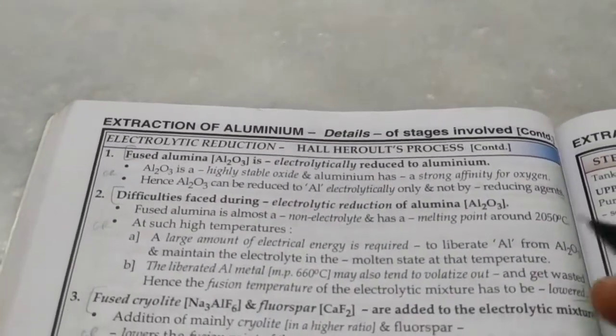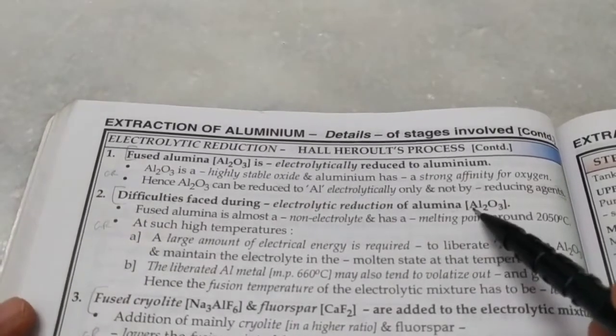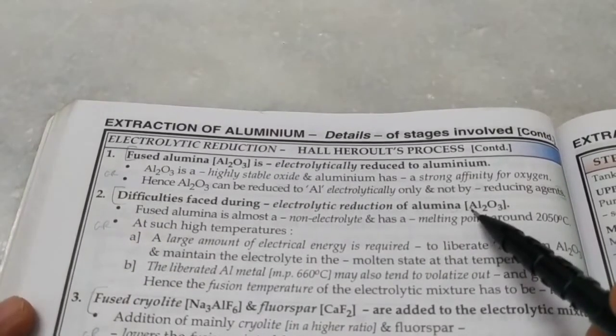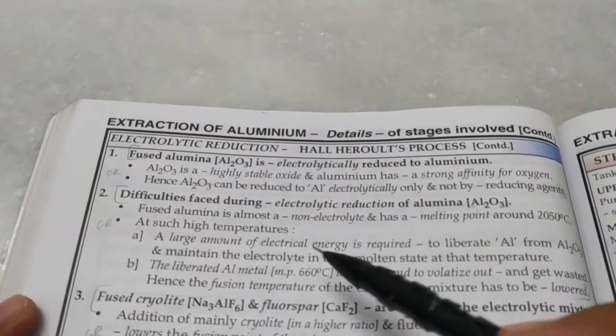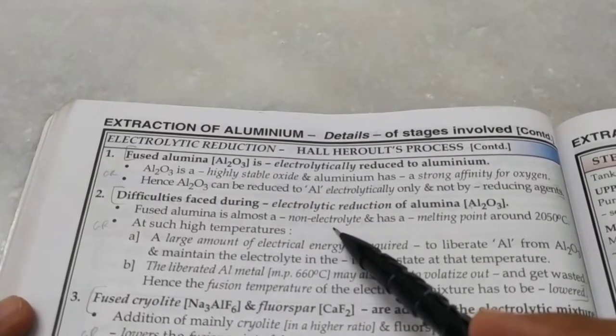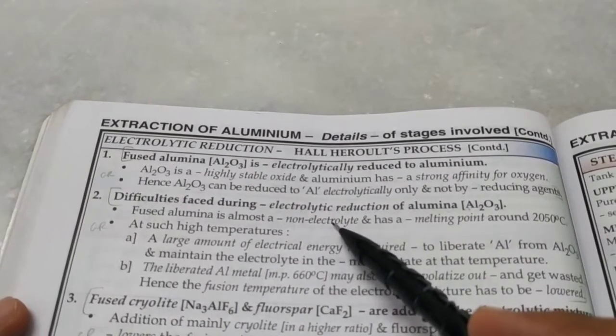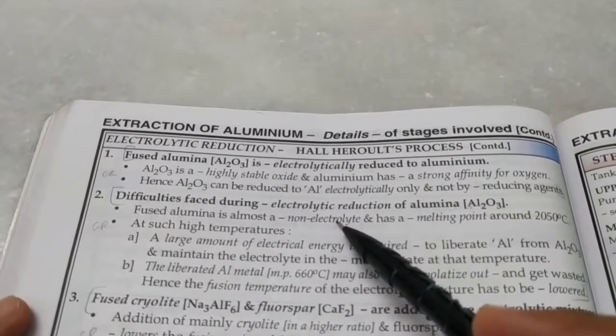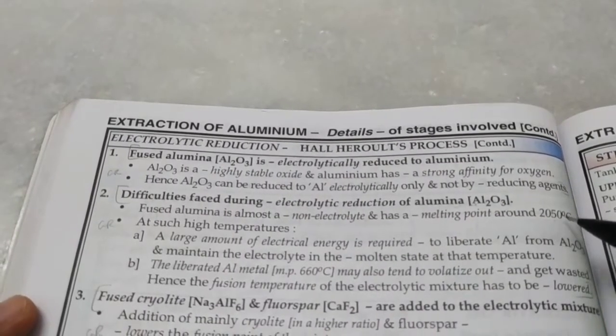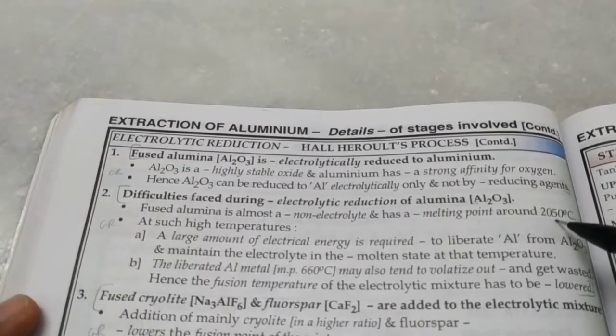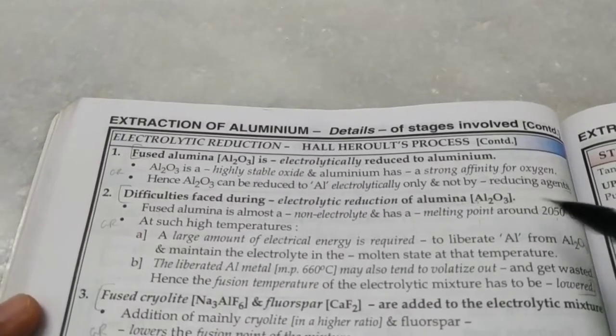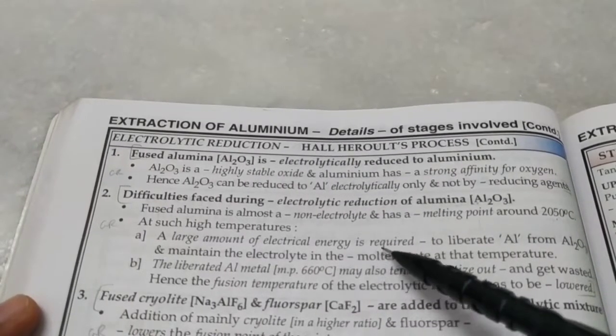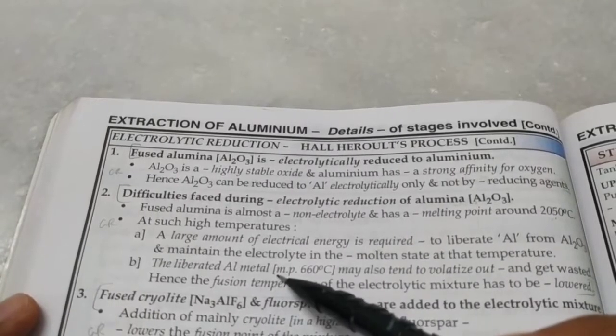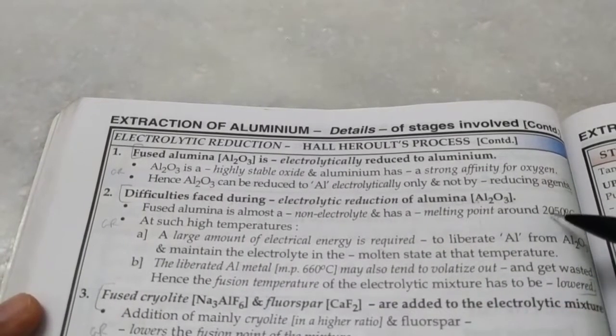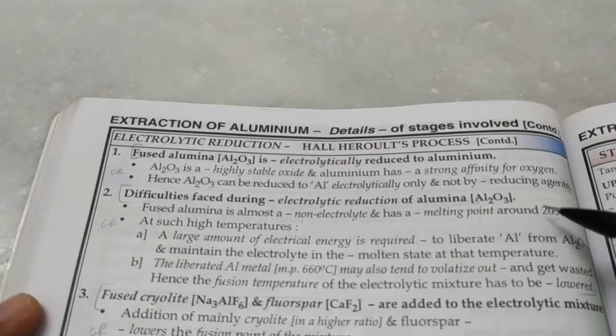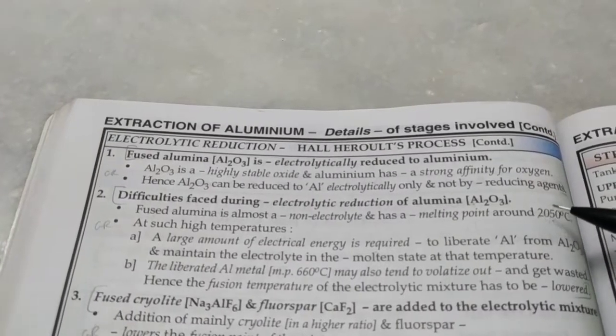First of all, if we had used only molten alumina as an electrolyte, that would have some problems associated with it, because fused alumina is almost a non-electrolyte. It hardly provides any ions. Its resistance is quite high. And its melting point is around 2050 degrees Celsius. It's so high to be maintained. And at such a high temperature, a lot of electrical energy will be required. Also, the aluminium produced, some of it might just evaporate at such a high temperature. So we need to add something to reduce the melting point of the electrolyte.